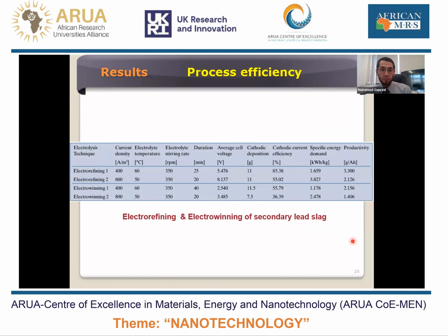lead nanopowder. If we compare two techniques, electrorefining and electrowinning: in electrorefining we dissolve the secondary lead in an electrolyte, mainly an acid containing chlorine, or we do electrowinning directly, adding it in the cell, where it dissolves in the electrolyte and deposits directly on the cathode and so on. We also optimized the production of lead nanopowders using these two different techniques.